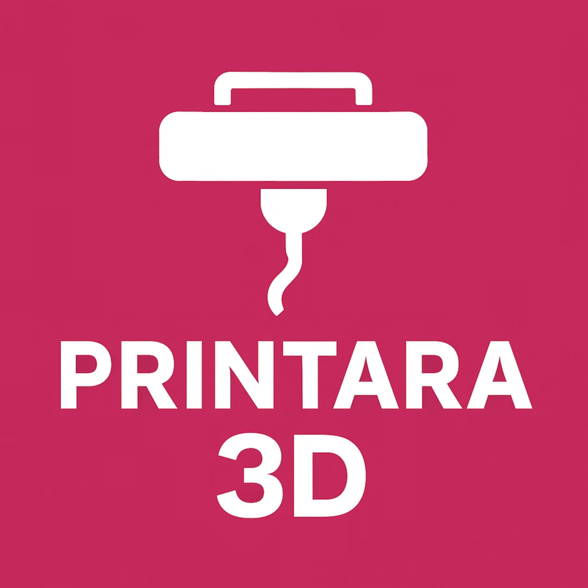If your flow rate is off by just 3%, you will suffer ugly overextrusion, particularly visible on top layers and overhangs. Flow rate is essentially the slicer's core math for volume. It calculates exactly how much plastic needs to be pushed to fill a space. Yes. The slicer assumes your filament is exactly 1.75 millimeters thick. But if your specific spool is actually 1.78 millimeters thick, or if the plastic expands slightly more than expected when it transitions from solid to liquid, you end up pushing significantly more volume of material than the slicer intended.